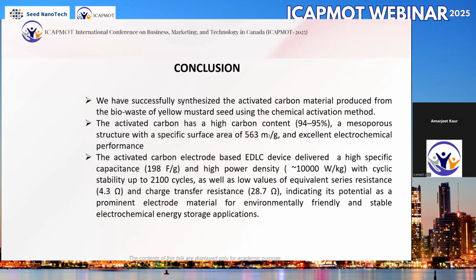In conclusion, we have synthesized activated carbon material produced from the biowaste of yellow mustard seeds. Using this carbon, the device has a mesoporous structure with a specific area of around 563 square meters per gram and very good electrochemical performance. It has a high specific capacitance of 198 farad per gram, a high power density of 10,000 watts per kg, and a cyclic stability of 2100 cycles. The best thing is that we have obtained a very low series resistance, and the charge transfer resistance is also 29 ohms, which indicates its potential as a prominent electrode material for environment friendly, stable, sustainable electrochemical energy storage devices.